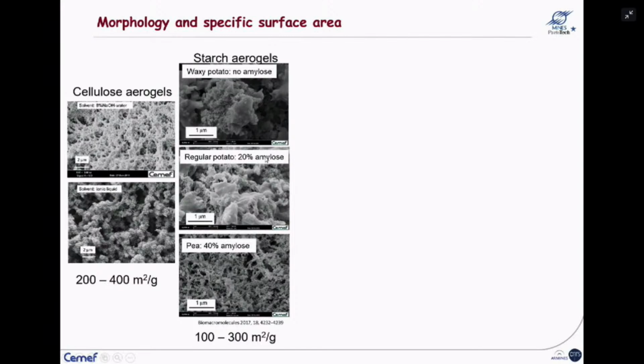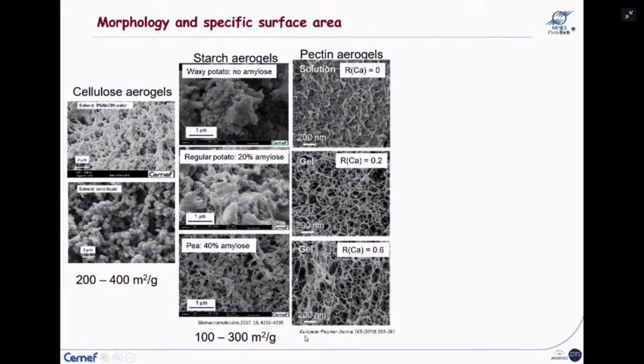Then when you increase the amount of amylose, which is a linear polymer and has a special kinetics of retrogradation, so there is an interplay of when amylose, amylopectin is gelling with different kinetics and so on. But you see that the morphology is very different with fine network when there is a certain amount, let's say, of amylose, also with a rather high specific surface area.